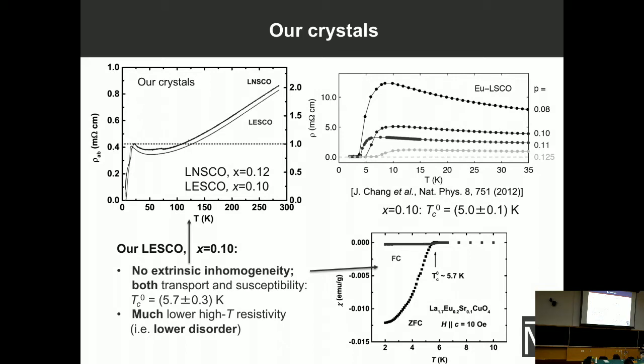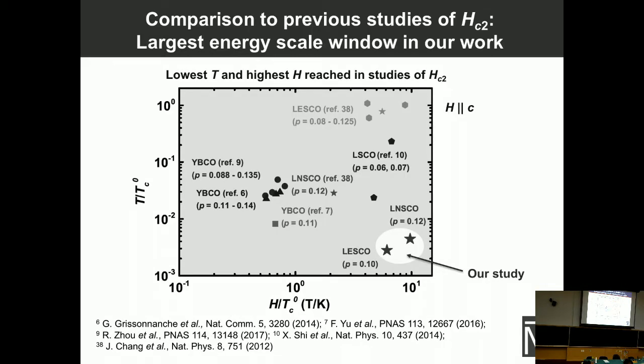So the low Tcs of these materials have allowed us to explore a much larger energy scale window compared to previous studies. To illustrate that, we have made this sketch, which shows the lowest temperatures and highest magnetic fields reached in various studies on this topic. And our results are shown here. Clearly, you can see that we reached the lowest temperatures and the highest fields, but not only that, we have actually explored the highest range of parameters. So we've mapped out the properties of the system in this rectangle here for this material, for example.